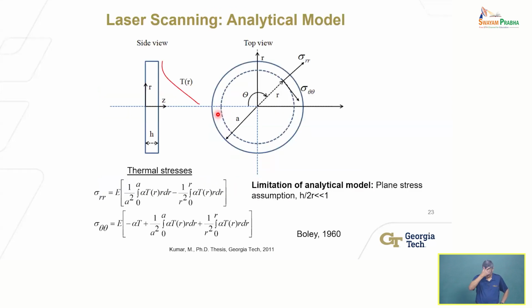So this is the analytical model. It exists. In 1960, somebody worked this out. Boley worked this out. There are some assumptions, obviously. Any analytical model, you make certain assumptions. The assumption here is a plane stress assumption, which says that H over 2R, where R is the radius of the region that is actually being affected by the thermal stresses, and H is in this case the width of this region. So they were looking at a disk, essentially, right? So there's an assumption of plane stress, which we may be violating a bit, but as a first approximation, it's an easy model for me to use, right?